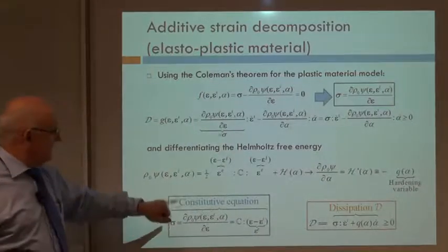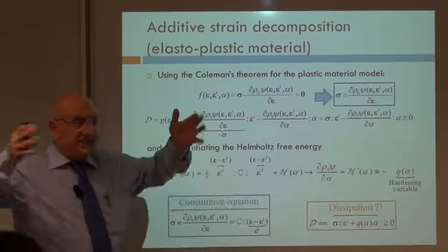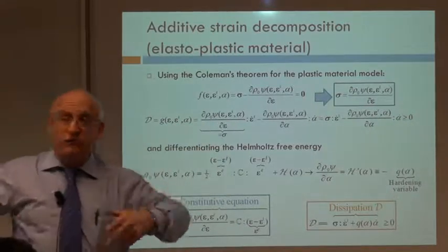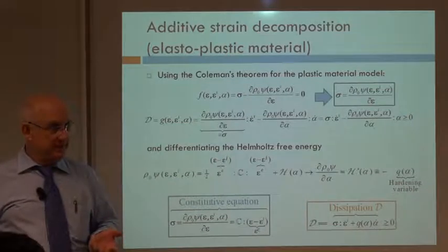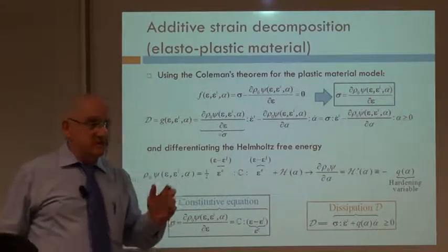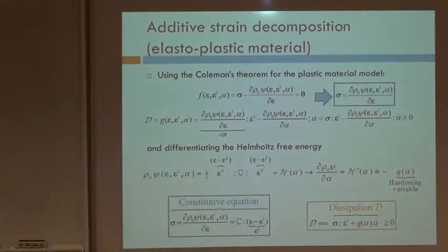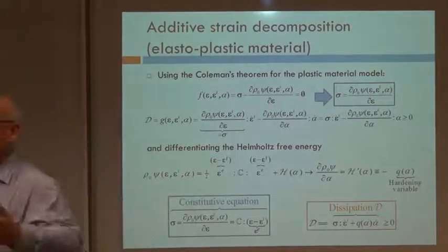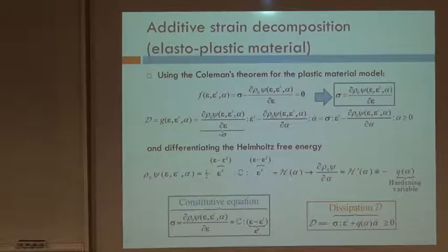So what characterizes the stresses is that they are equal to the elastic constitutive tensor, the same that we would use for an elastic material, but now multiplying not the full strain, but the elastic part of the strain. So that's very easy to remember. In any inelastic material based on the additive decomposition of the strains, the stresses and the elastic strains are related as in an elastic model.